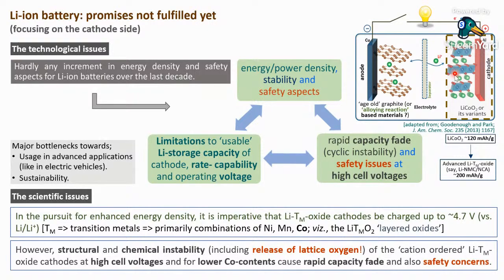Now, after a lot of work over the last 25 to 30 years, we now have cathode materials which have a capacity of about 180 milliampere hour per gram in a practical context. So the cathode capacity is still half of that of the anode capacity, and the cathode is still the bottleneck in terms of increment in the cell capacity and thus the energy density. So one needs to enhance the cathode capacity. In other words, being able to take out more lithium, because this acts as the reservoir. To start with, all the lithium ions are present in the cathode material. So one has to take out the lithium ion, and the more lithium ion one can take out, the greater will be the usable capacity.